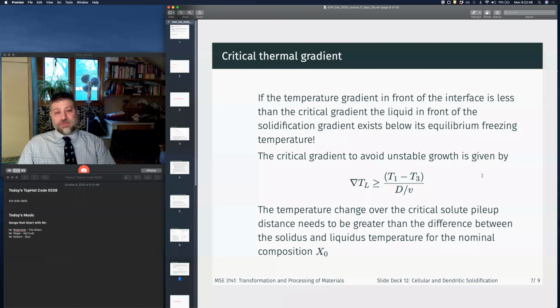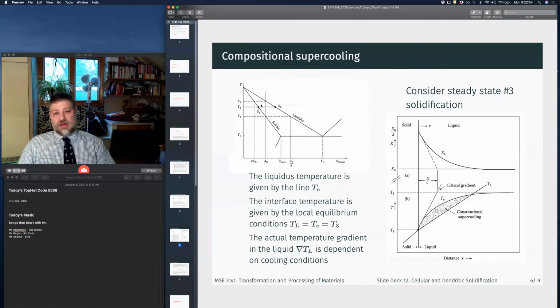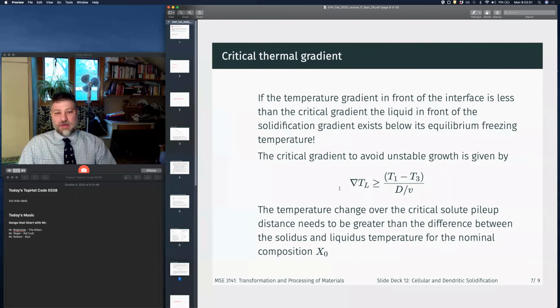So the critical gradient to avoid unstable growth has to do with this freezing range, T1 to T3, which is the freezing range for this alloy composition, divided by the width of this pileup. The gradient basically says I need a temperature gradient that's steeper than my freezing range divided by the width of this pileup. This way I'll avoid any compositional undercooling.